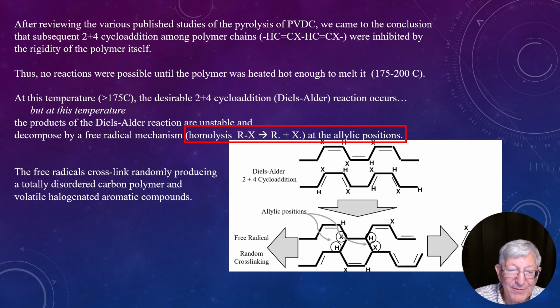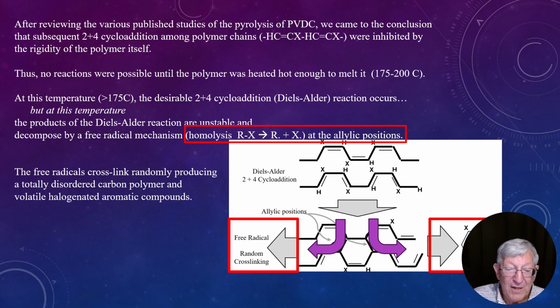And when that happens, it gives you free radicals. It gives you chlorine radicals. It gives you carbon radicals. And this is where the random interchain connection starts. And so you end up getting random cross-linking. And you can also get trichlorobenzene, which is one of the byproducts that comes out of these things when you heat it up this way. And so the idea is, how do we prevent this from occurring?